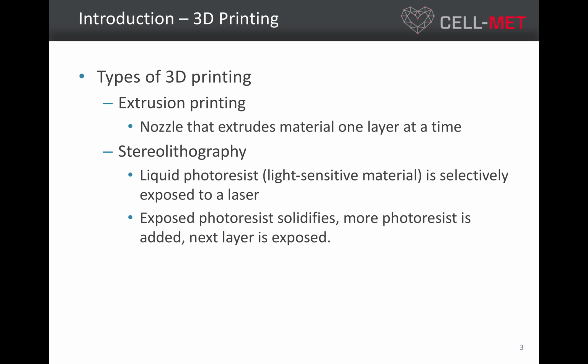The other type is called stereolithography 3D printing, where you have a giant bath of liquid photoresist, which is a light-sensitive material, and you selectively expose parts of this bath to a laser, layer by layer. And once the photoresist is exposed to this light, it solidifies and it hardens. So then more resist is put on top of that, and you do the same process again where you selectively expose. And through this process, this layer by layer approach, you end up coming up with a part which can look exactly like an extrusion printed part. It's just a different method of doing it.